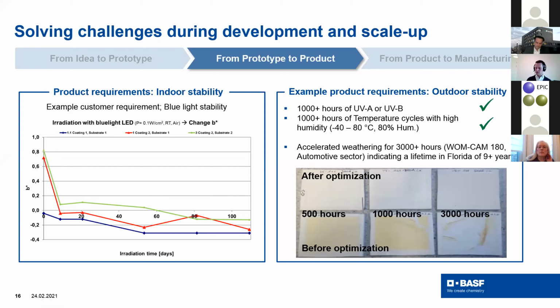a lot of outdoor stability questions or requirements. And then you're talking about 1000 hours of UVA, UVB stability, temperature cycling with high humidity. Or here at the bottom right, I brought one example. It's a test from the automotive sector. It's called WOMCAM 180, which has a very high UV dose, temperature cycling, it has rain on top, and it has a nice correlation on a car, of course. Every 1000 hours of this test roughly is 3 years of use driving around in Florida.